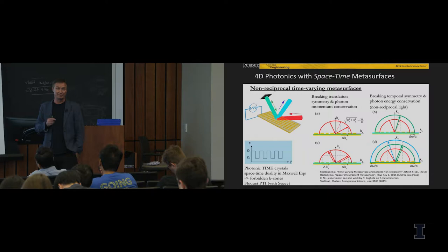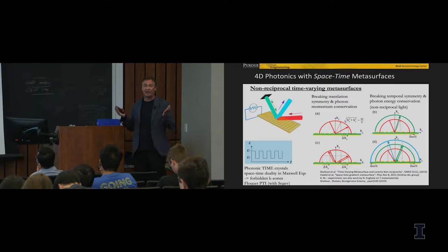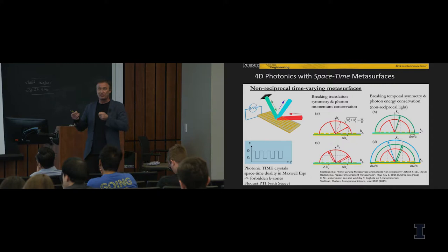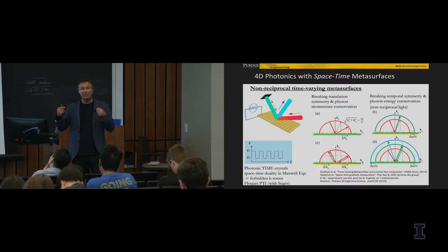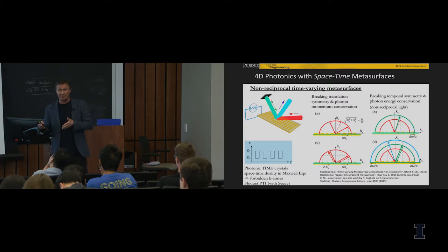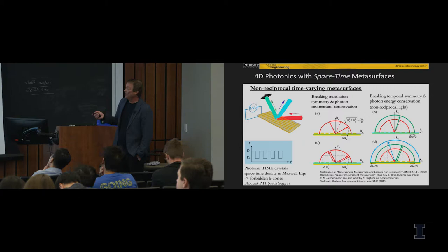So what if I have now a metasurface where I modulate my phase not in the space domain, like in conventional metasurfaces, but in the time domain? So I introduce a gradient of phase in the time domain. But a gradient of phase in the time domain means a shift in frequency. It's like a Doppler shift, for example. So what happens in this case, let's say, if my initial frequency was such that the iso-frequency surface is given by this red curve, light is incident on this metasurface modulated in the time domain. Because of the shift in frequency, you would get a different frequency. So that's my new iso-frequency surface.